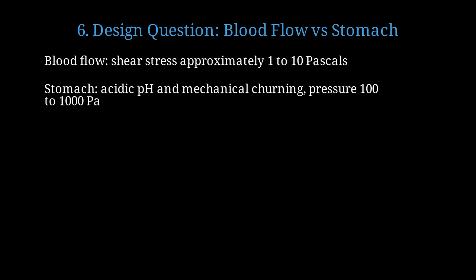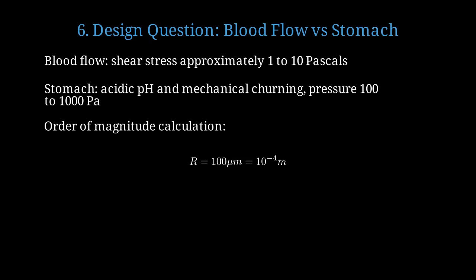In blood vessels, capsules experience shear stresses of 1 to 10 pascals from flowing blood. In the stomach, capsules face both acidic conditions and mechanical pressure of 100 to 1,000 pascals from churning. Let's do an order of magnitude calculation to estimate the required shell thickness. Assume capsule radius of 100 micrometers, which is 10⁻⁴ meters. Typical polymer elastic modulus is around 1 gigapascal or 10⁹ pascals. Blood pressure is 10 pascals. Stomach pressure is 500 pascals.